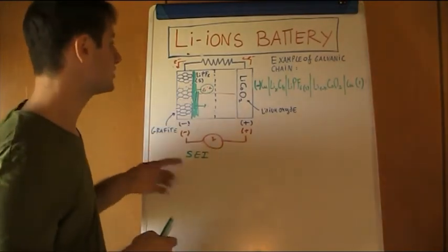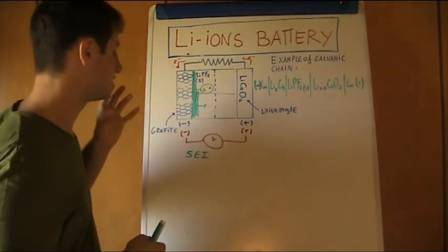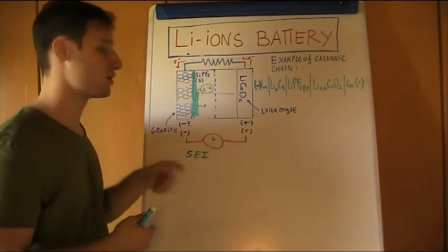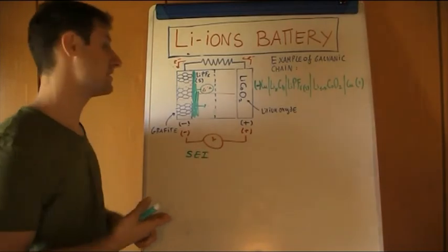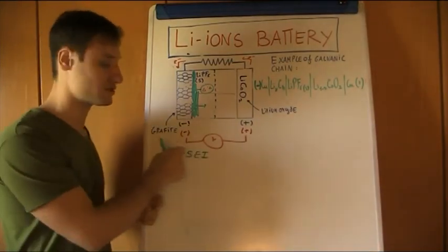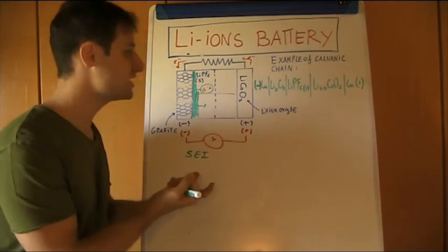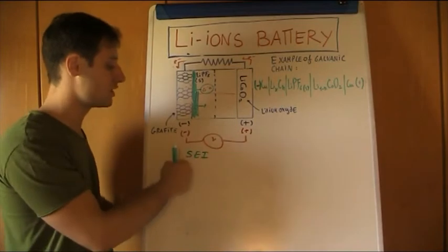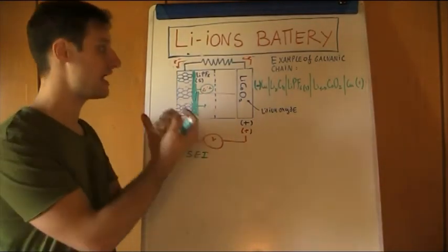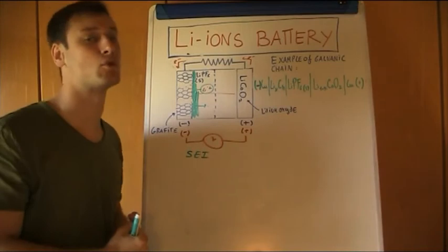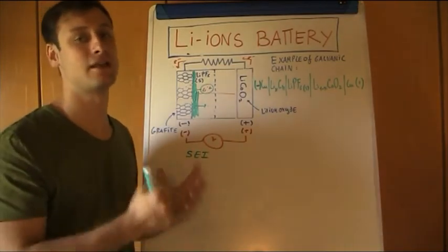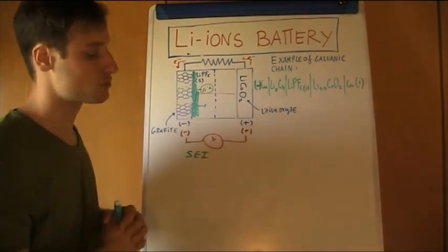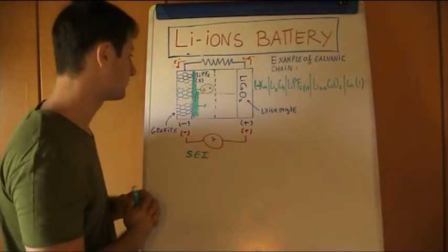So basically the reason for which we have the self-discharge is due to the tunneling of electrons over this type of protection layer, but that causes an expansion in the thickness of this layer itself. And when we are using it, we are promoting the speed at which the expansion of this solid electrolyte interface occurs, and so the battery will die in a shorter time if we are using it a lot. So basically we have defined more or less all the main important concepts concerning lithium-ion batteries.